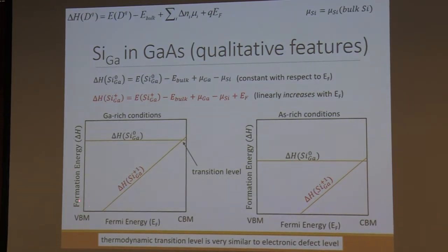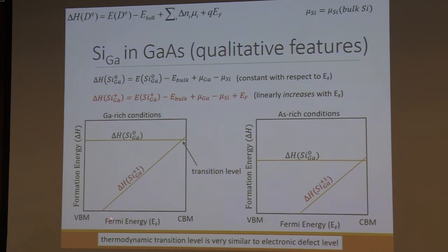So this says, okay, we're assuming that the Fermi energy is somewhere between the valence band of the material and the conduction band of the material. It's very hard to push it too far out of those bounds. So the neutral defect in this case would be when you don't charge pump? Yeah, you don't charge. You just put it in, and that's it.